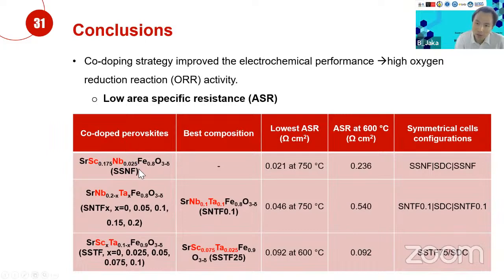So in conclusion, we have discussed 3 different materials. The best composition for the second family will be the SNTF 0.1. And the best composition for the third family will be the SSTF 25. The lowest ASR is obtained by, well, the temperature is a bit different, but I would say that the best cathode among these 3 is the SSTF 25. And then we have tested the ASR in the symmetrical cell configurations.